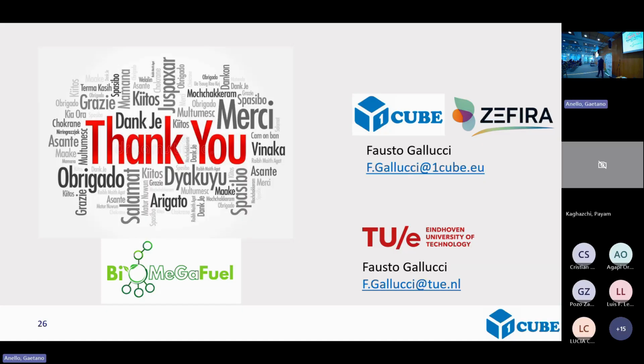Absolutely. Water is smaller than hydrogen as a molecule. Many people don't realize that. That simple molecule, hydrogen, has a kinetic diameter that is bigger than water. So in principle, it's relatively simple if you have pore sizes that are all the same and lie between hydrogen and water. This would be possible with zeolite, if you don't have defects, as Hannes showed.